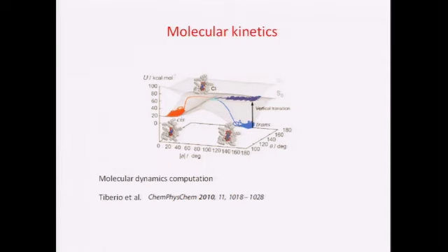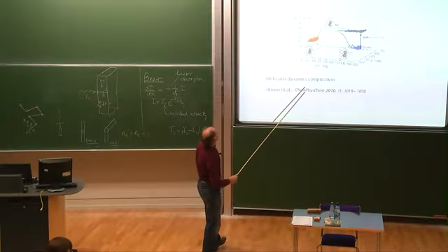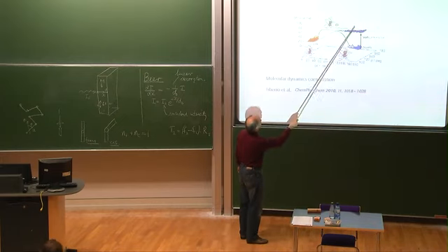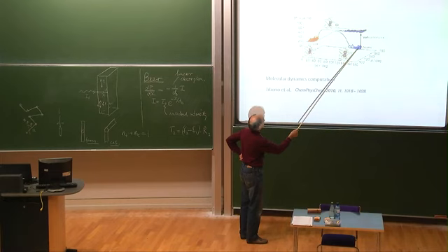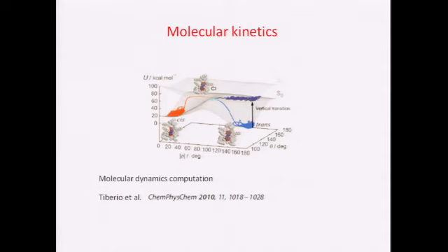It's probably worthwhile looking a little at what the molecular kinetics of the process going from trans to cis looks like. This is a computation by Claudio Zanoni and his people. They have actually considered not the main optical transition at 350 nanometers, but a weaker one at somewhat longer wavelength, which goes to the closest excited electronic state. So anyway, it first goes from the trans electronic ground state to the first excited state.